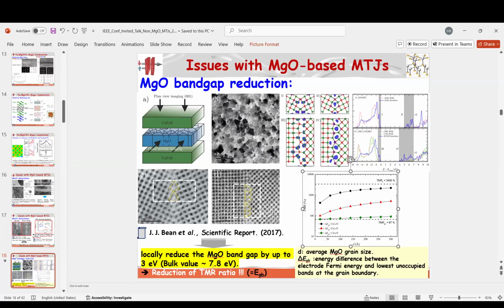So it's not the bulk value of 7.8 electron volt, but rather it has 3 electron volts. So in my understanding, this is a new MgO with a lower band gap, and that's what really explains the saturation. I should apologize if I didn't bring this.